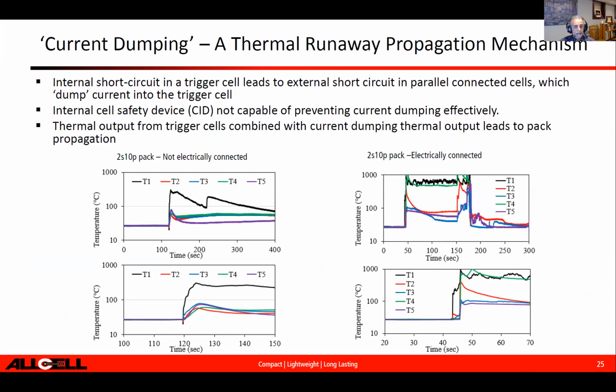And as you can see here, we found that in those cells that are electrically connected, you see a significant amount of current rush and significant amount of heat of the adjacent cells compared to ones that don't, as shown in this graph, with 2 cells in series and 10 in parallel. And what that tells us that there's something, not just the thermal runaway that happened to the cell, but the current that exactly rushes because of that cell that failed was electroconnected to the rest of the pack, what causes a lot of those heating issues.